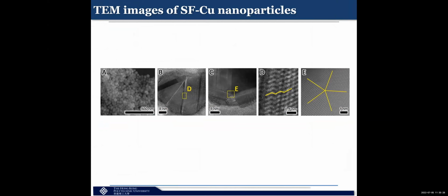Okay, we have done a series of characterization. We found that on the surface of this nanoparticle, they contain many step facets, or stacking faults, so-called. It depends on how you call it. And this kind of surface morphology is very good for CO2 reduction, and can also improve the Faradaic efficiency for the C2H4 product. From the TEM, we can see all these stacking faults, and there is a twin type of grain boundary as well. It depends on which location you look at.